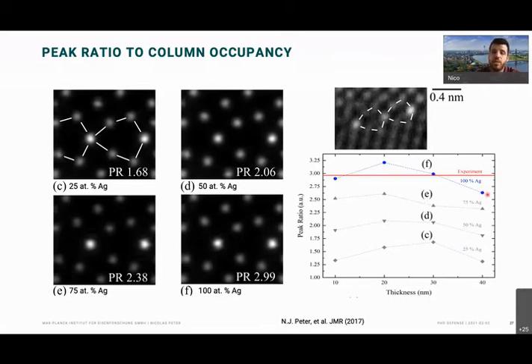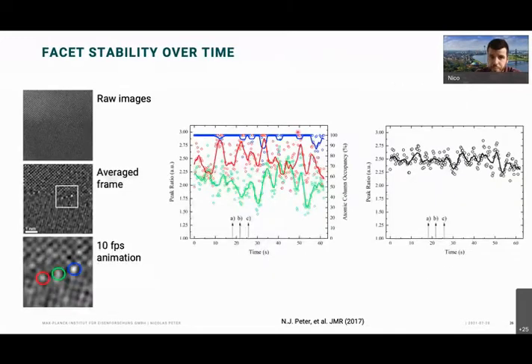And actually for a 100% silver, so a full column, we see that this matches very much the peak ratio value that we find in experiment for a 30 nanometer thick sample. So this is also the thickness of our samples that we typically observe. So that makes sense. So this is how we relate, okay, this blue column that I showed before here is actually 100%. And based on the rest, we can then have a scale of how much silver there is in the column.